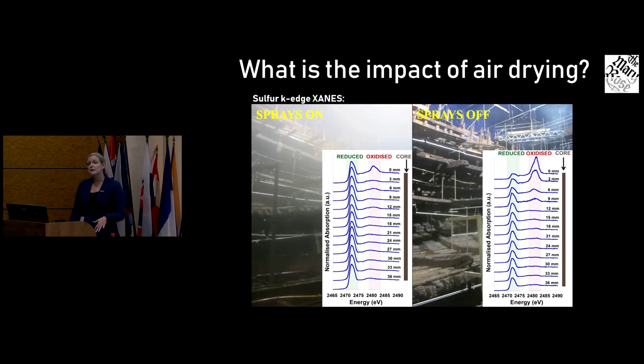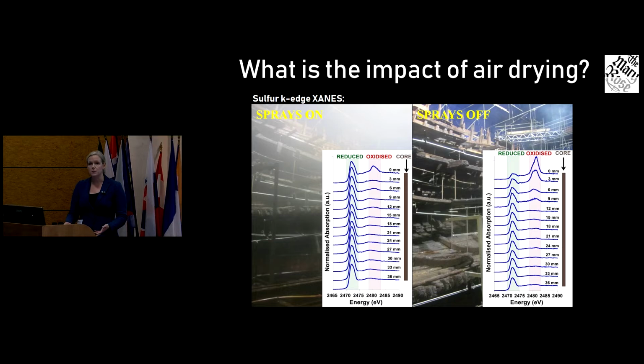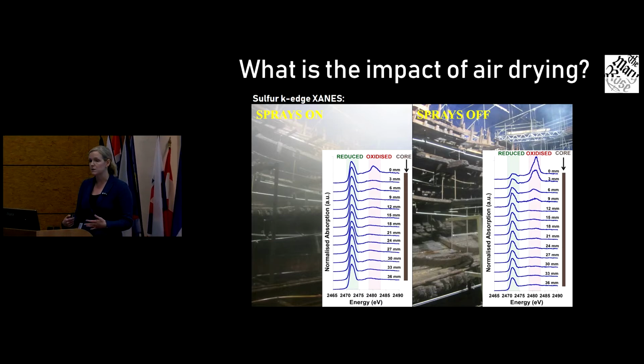Now, the wood itself, the ship is in very, very good condition considering everything that it's been through. But typically with these materials, you do have to do some kind of consolidation treatment to compensate for the loss of the wood material. In our case, we treated with polyethylene glycol, and once that treatment was finished, we then needed to dry it to remove any residual water. Now, obviously, the worry with that was we were then going to expose it to air, to oxygen, and we knew that sulfur was in the timbers and that this could transform and cause us problems.